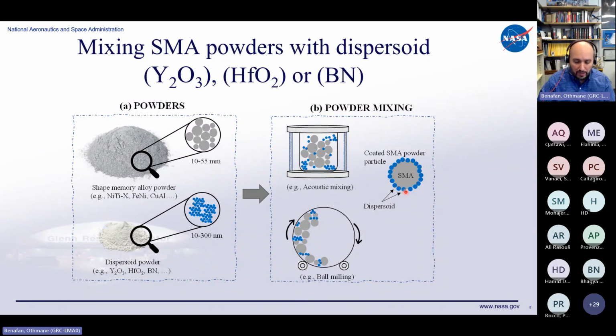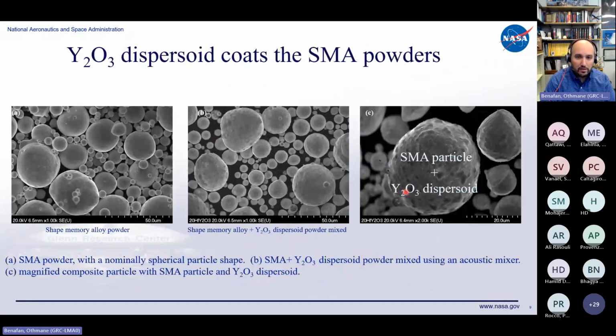How does it work when you do this process from a powder level, before we even go to the additive manufacturing side of things? It looks like this. From the left here, this is the regular powder, just SMAs. There's nothing applied to it just yet. Then we add some weight percent of yttria, as shown in the middle here. The powder is still spherical, but here it has these things adhered to it. And if I zoom in, you can see some of the yttria coating the SMA powder, in this case a nickel titanium alloy.